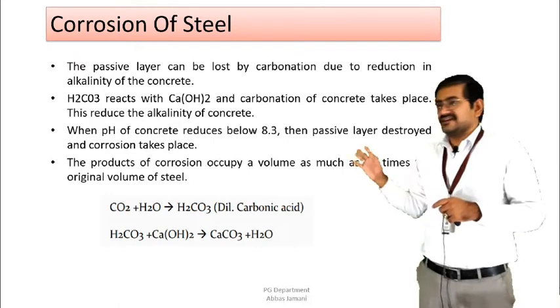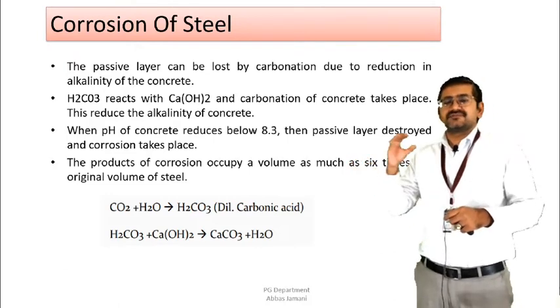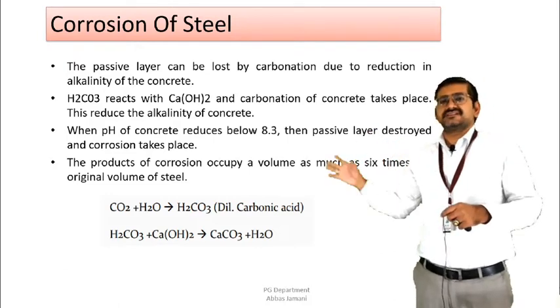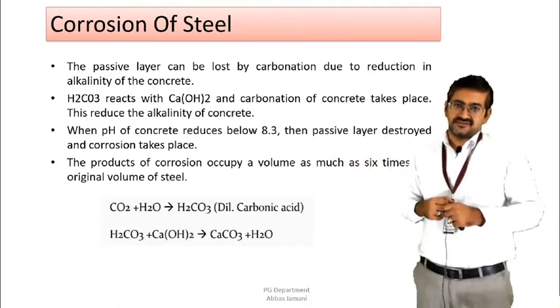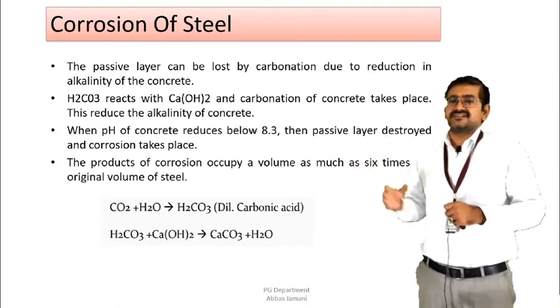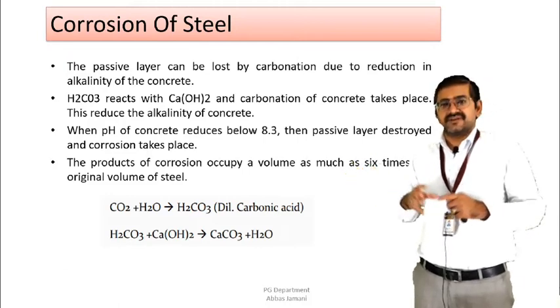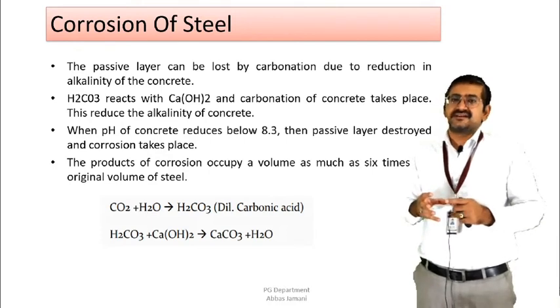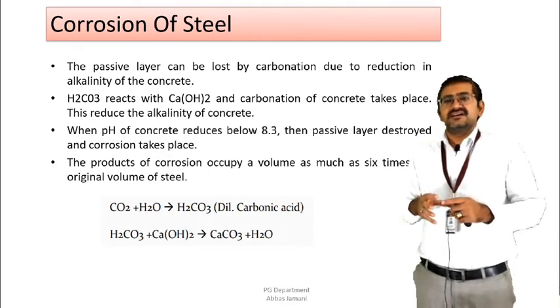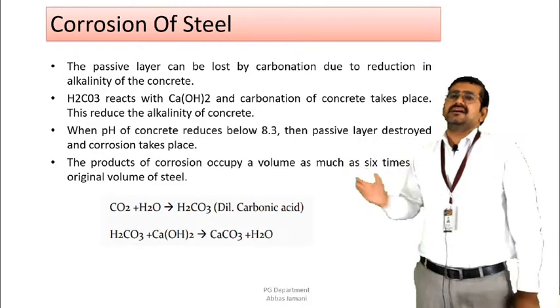The increase in volume is almost 6 times, so it is likely to try and occupy a similar space in the concrete structure. If that space is not available, it will exert pressure on the surrounding surface. As a result of this pressure, cracking is initiated, followed by spalling and then delamination.